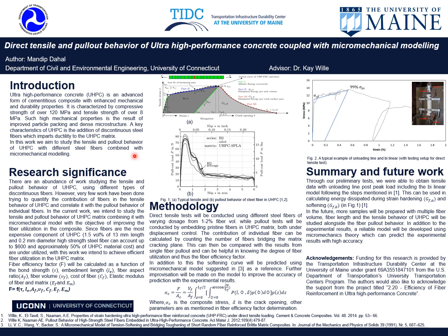Now, the methodology. To explore the fiber efficiency in UHPC, we will conduct the direct tensile test using different types of fibers at different dosages from one to two percent of the fiber volume. Also, we will conduct the single fiber pullout test by embedding the pristine fibers in a UHPC matrix.